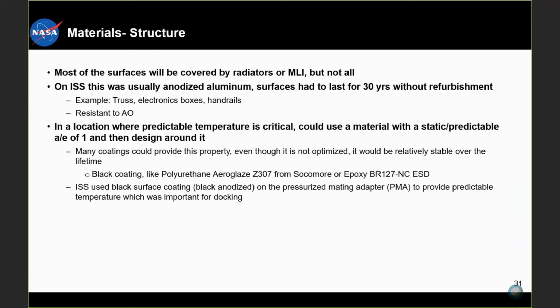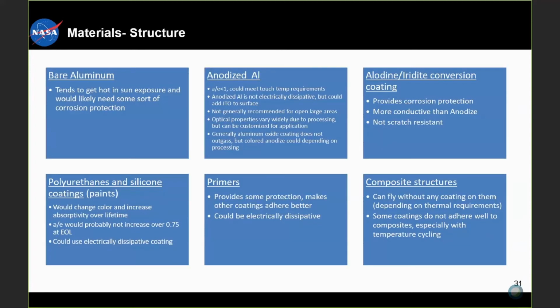A rule of thumb is that in a location where a predictable temperature is critical, you could use a material with a static or predictable absorptivity to emissivity ratio of 1, and then design around it. Many coatings actually do provide this property. It's not optimized though, but it could be relatively stable over the lifetime. For example, one of these is a black coating, like polyurethane Aeroglaze Z307. ISS used a black surface coating, which was black anodized, on the pressure mating adapter to provide predictable temperature, which is also important for docking.